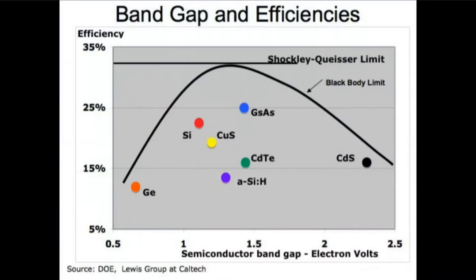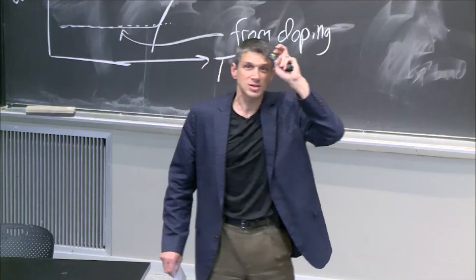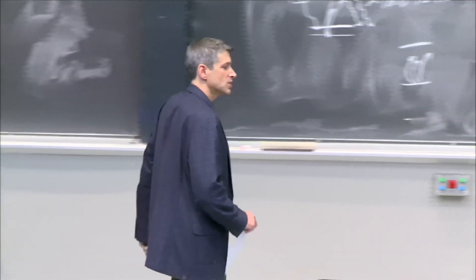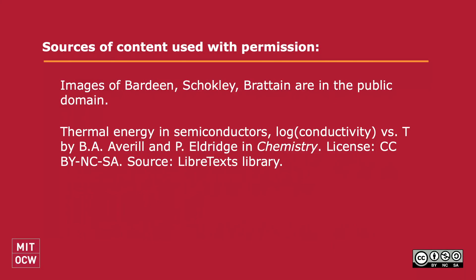And that's what is plotted here. This is the band gap of a semiconductor, and this is the maximum that that solar cell efficiency could be. That's the maximum that it could be for that gap. So you can see the sweet spot is right there. That's a thermodynamic derivation called Shockley-Queisser of the maximum efficiency you could ever get out of a single material. And notice, if you put the materials here, silicon is 90% of the solar cells you buy today. And notice that it's not quite at its maximum potential. It's also not quite in the middle where you'd want. It should have a slightly higher gap. You get to higher efficiency. But these materials out of gallium arsenide, they do have the right. What is GaAs? That's not an element. Gallium arsenide, it does have a better gap, but it's much more expensive. And so we go, and a lot of solar cell research is on getting as close to this point as you can.